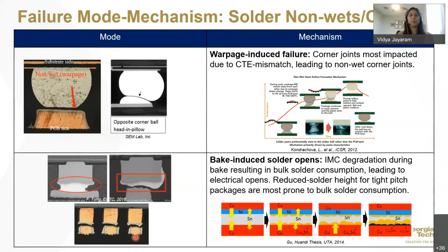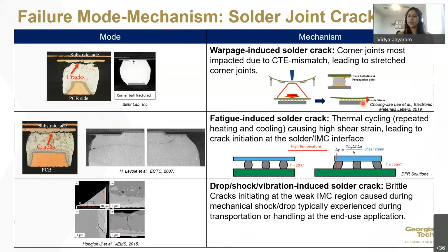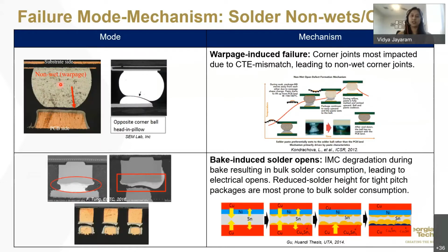And moving to the solder non-wet and open, again, there can be multiple mechanisms. The first one here is, again, warpage-induced failure, similar to what I mentioned in the previous slide, where because of the high CTE mismatch, you would see either a smile-shaped warpage or a frown-shaped warpage. For example, for a smile-shaped warpage, in the previous case you had a tensile stress that the bumps experienced because of being stretched, but there can also be cases where the corner bumps don't touch the pads, and that can lead to a non-wet or an open circuit.